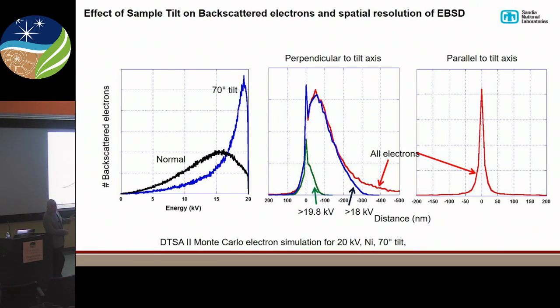And remember, when we're doing diffraction experiments, you'd like a monochromatic beam of whatever, X-rays or electrons. It turns out when we tilt to very high angles, like 70 degrees, those electrons go into the sample and come back out without losing very much energy. And those are the ones that form our diffraction pattern. So that's why we can use this technique to do diffraction, because we now have almost a monochromatic source of electrons that we use to illuminate our sample and form our patterns.